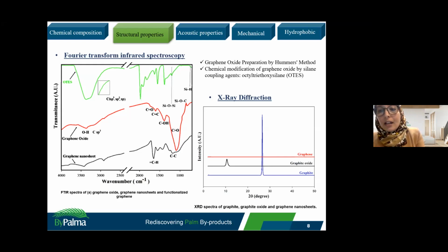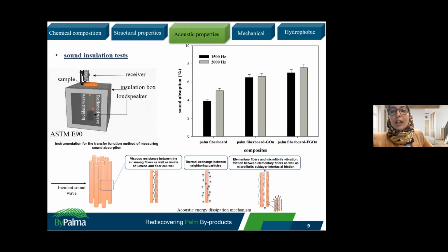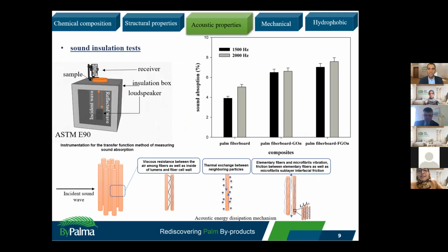This group is related to the alkylated group in the silane molecules. So here we have the sound absorption measurement, which is performed according to the ASTM E90 standard at tube frequencies of 1500 and 2000 Hertz. The tested sound absorption coefficient of the fiberboard composites is presented in this figure as a function of composites and frequencies.